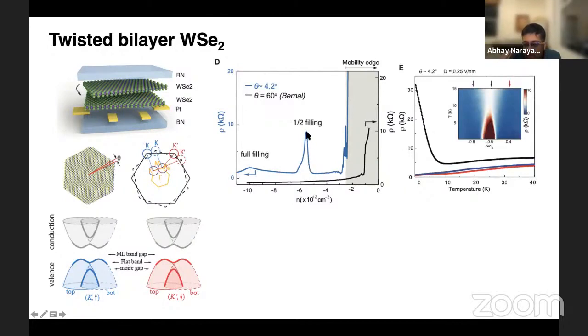If you're not sitting exactly at this half filling point, but I'm sitting somewhere here away from this half filling point, if you measure the temperature dependence is essentially monotonic and occasionally goes to 0, although we are yet to confirm that it's superconducting.